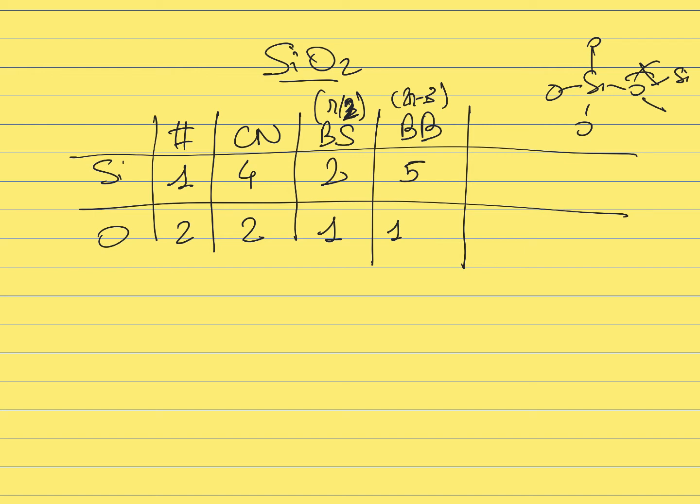And that's pretty much the only case where you will see that kind of phenomenon. Since this glass has such a high glass transition temperature, this constraint becomes thermally broken. It means that this angle, the angle between silicon tetrahedra, the angle around the oxygen, will have a great variability in silica.